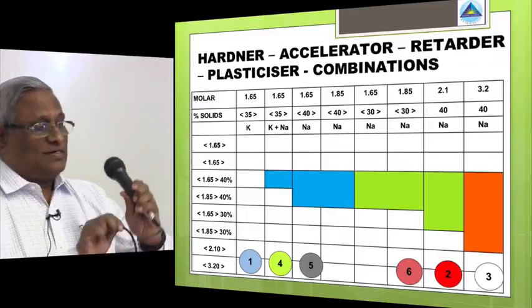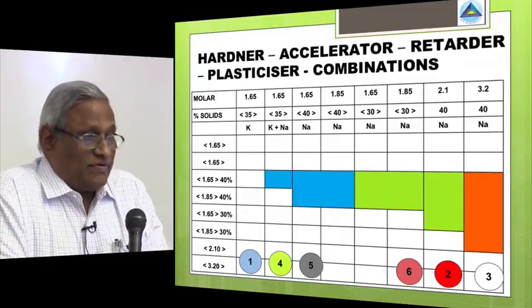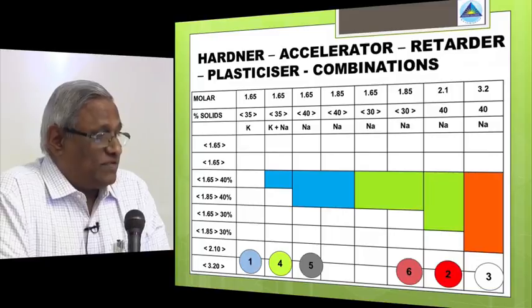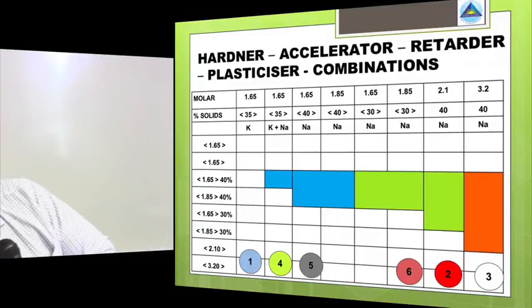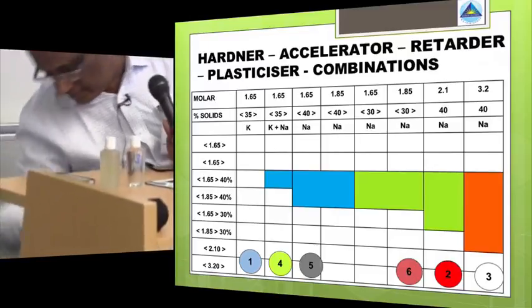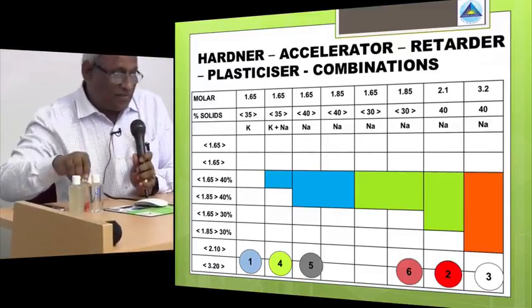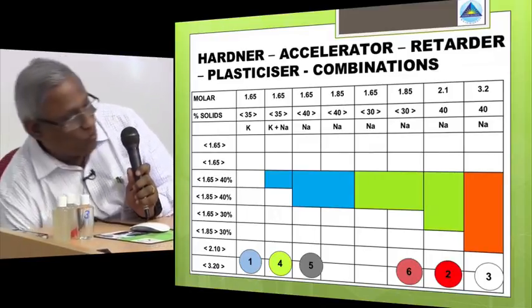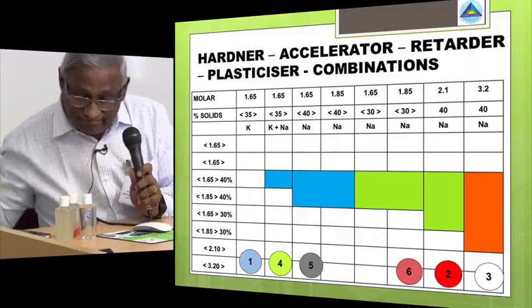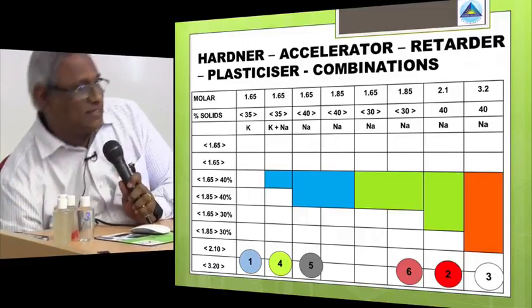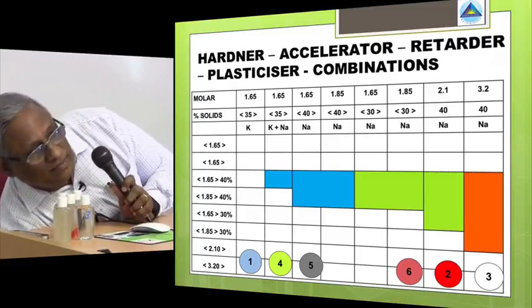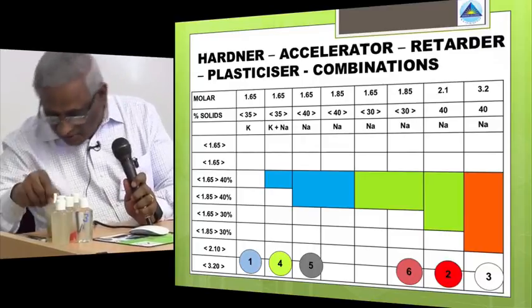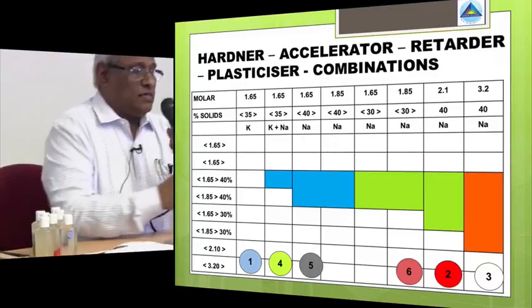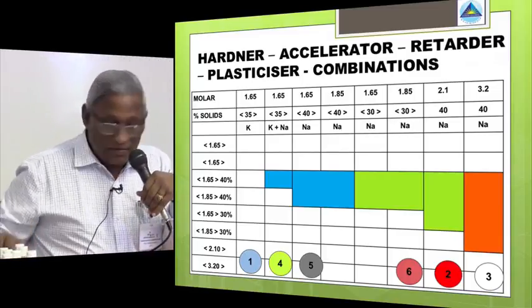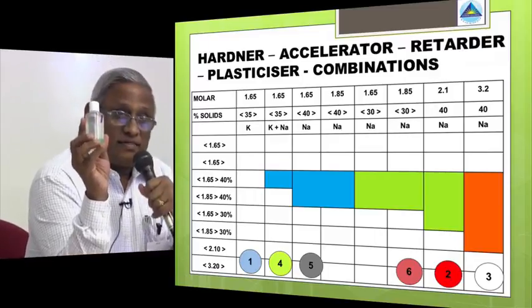This is something very important, and the type of accelerators we have used, the retarders we have made, and on different molar ratios. See, I have the samples here which I'm going to show to you, on different types of silicate. We make from molar ratios of 1.65 to 3.2. Many of the people will wonder what the 3.2 will do here, because the recommended ratios are 1.65 to 2.1. You see, the one I have is this, the 1.65 ratio with the 35% solid content.